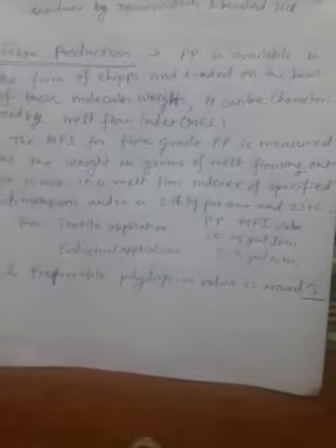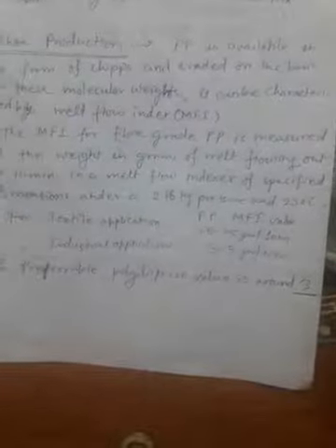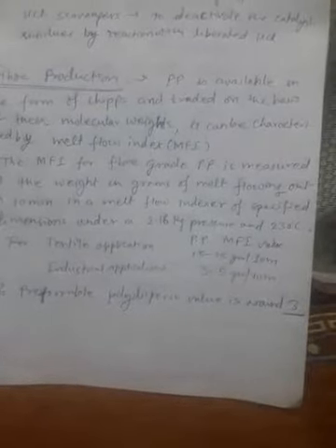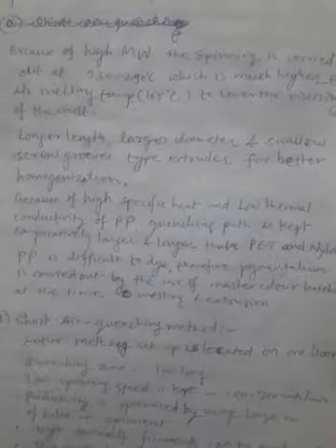And here the preferable polydispersity value is 3, and polydispersity values of 2 to 15 are available. Now, for fiber production techniques, melt spinning is carried out mainly, and here some points need to be discussed, because of the difference in polymer quality from the rest, the nylons and polyesters. You can see the melt spinning is carried out at 230 to 290 degrees centigrade, which is much higher than its melting point of 165.